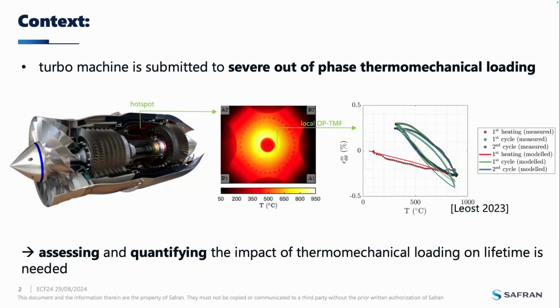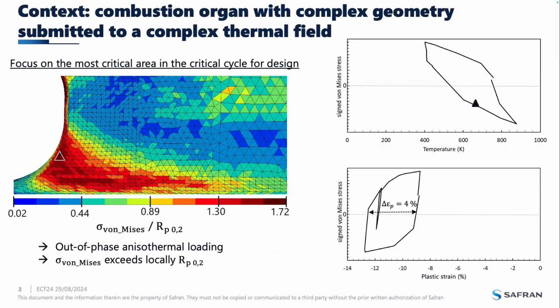In turbo machines, some hotspots are locally submitted to severe out-phase thermomechanical loading, as you can see. So assessing and quantifying the impact of the thermomechanical loading on lifetime is needed. I am currently studying a combustion organ with a complex geometry submitted to a complex thermal field. Here, you have a zoom on the most critical area in the critical cycle for design. And as you can see, the loading is severe, as locally in the structure, von Mises stress exceeds the yield strength.